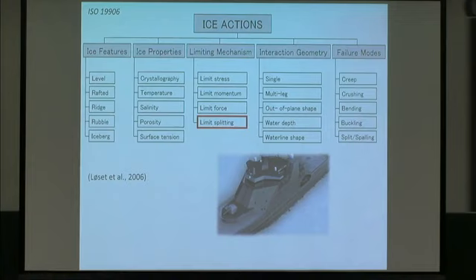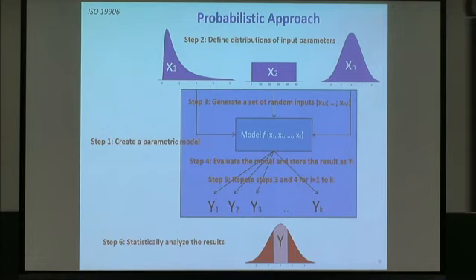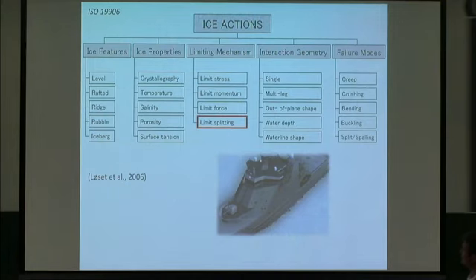So what concerns me with ISO, and I'm in one of the working groups there together with Bob, Fredriking and others, is that if you now think about loading from this kind of perspective, say that you have a probabilistic approach here and you have a certain parameter which affects you, a distribution of that one, another one, a third one, and so on and so on, and you need to create a parametric model here. And what is there very often is that you take a deterministic model here, which includes one failure mechanism. So it means that you go back here and you choose a failure mechanism, and then you start calculating for there. And that's completely wrong according to my vision and understanding, because that's not what we see. We see the combination of different failure mechanisms more or less at the same time. So I would say the problem with ISO here is they have no proper model considering that. And I will not go further into details in this talk, but for me it's at least a major concern.